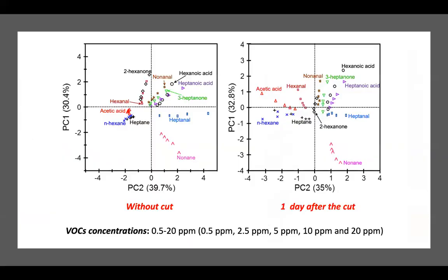The most important part, before my final two slides, is that this device doesn't only revive its electrical and mechanical behavior, but also its chemical sensing behavior. We have taken biomarkers from the skin before any cutting process, and the device could detect a wide variety of compounds at different concentrations and separate between them very nicely. We cut the device in the middle, reconnected it, and waited 1 day. Even after 1 day, the device still performed quite nicely and could differentiate between the biomarkers and their concentrations in a very significant way.